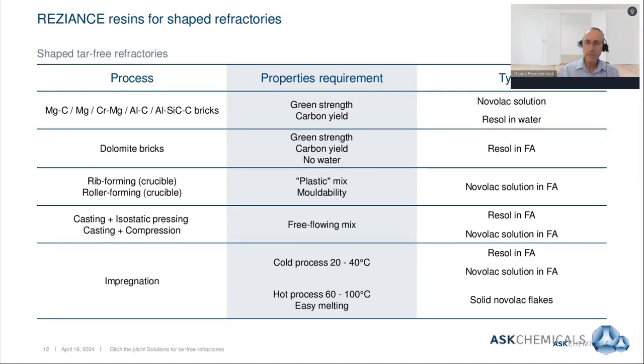I'll run through a few typical examples of the types of phenolic resins that you can consider using for the different types of shaped refractories or the different processes. In the case of the general types of bricks, we are referring to magnesite or mag carbon, chrome mag, aluminum carbon, and other types. The typical type of phenolic resin used would be a Novolac solution. And when we say solution, these could be in solvents, typically of high boiling point, but also sometimes liquid resol water based. Because what you're typically looking for in these cases would simply be green strength and a certain carbon yield at the end.